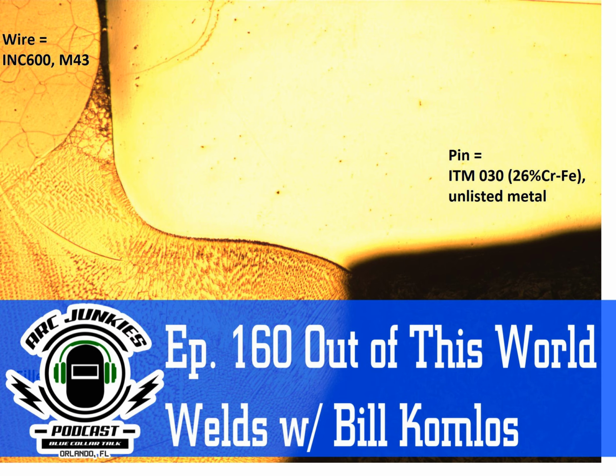I get in arguments all the time with people that are like, oh, no, I spray with 75-25 all the time. No, you don't. You've got to hit 26 volts and 82% or higher in your argon concentration. Otherwise, it's not happening. It's going to look similar, but if you zoom down in there, that's not what's happening. You're not getting into a spray transfer.